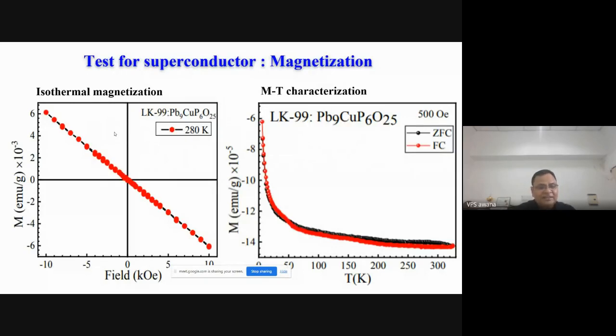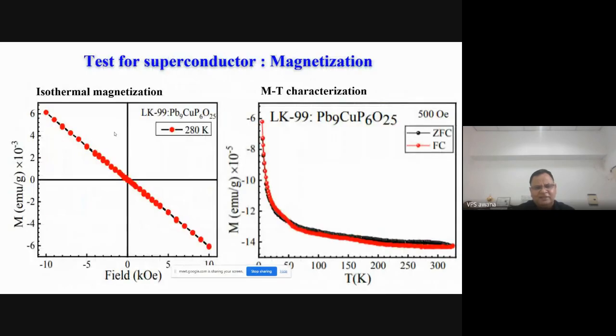The chunk of this LK-99 shows a perfect kind of diamagnetism. ZFC, FC, you can see diamagnetic and both are merging with each other. It's below 300 Kelvin, and even the M-H also shows the diamagnetism. There is no signature of superconductivity at all. We did actually its resistivity also. I will show that, and it was not showing R equal to 0 at all, in fact.